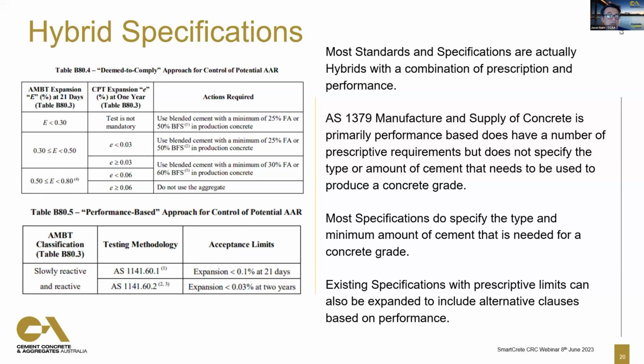But at the same time, in that specification, under certain conditions, you can use those same tests and work out how much SCM you want to use, fly ash or slag in this case, to reduce those expansions below the level that is acceptable for concrete use. So that's a really good example of a hybrid. If you're not sure how to design it, follow the bouncing ball and the deemed to satisfy rules. But if you've got some better idea to do it, then use the performance-based method to then give you a